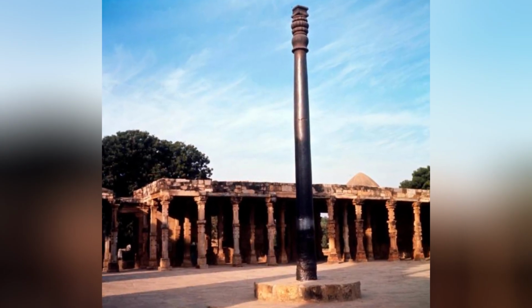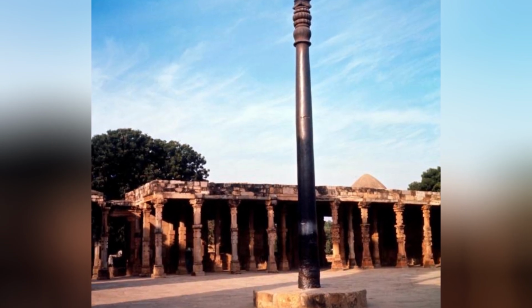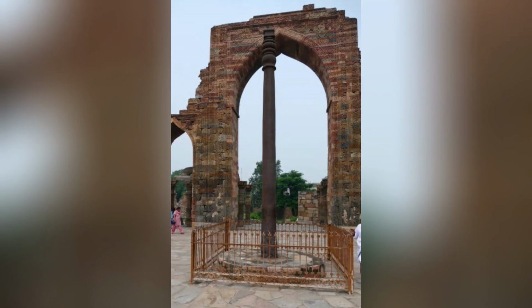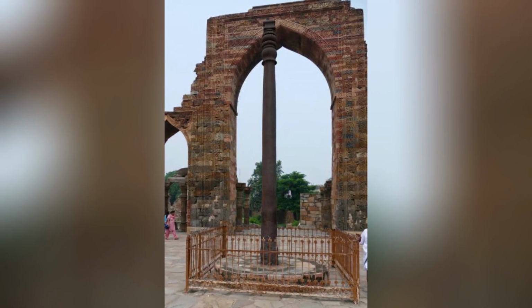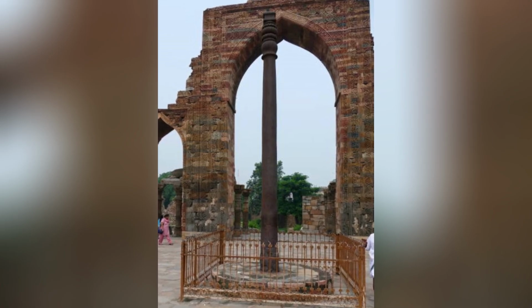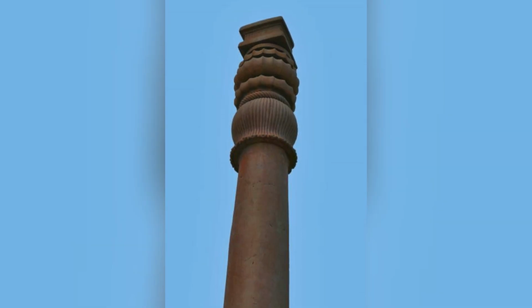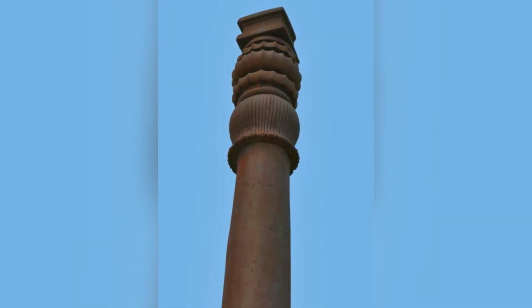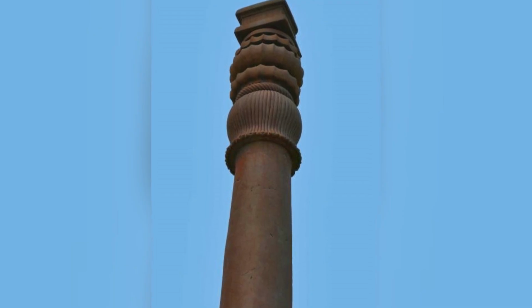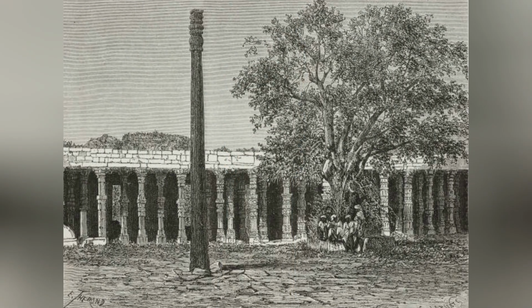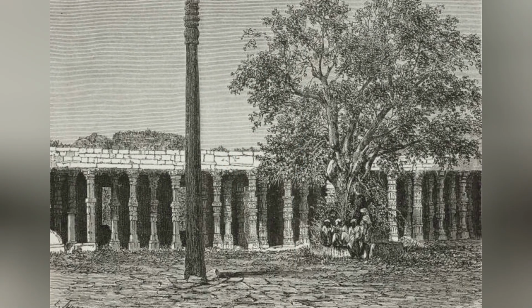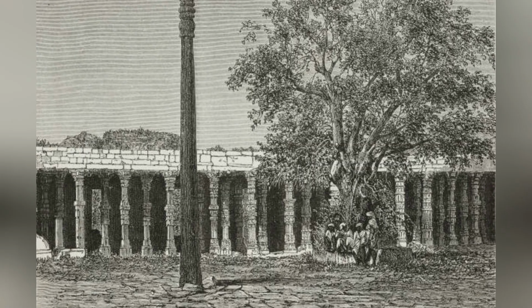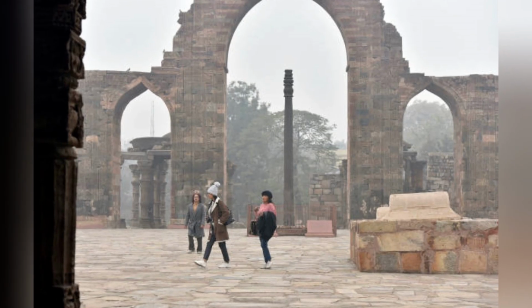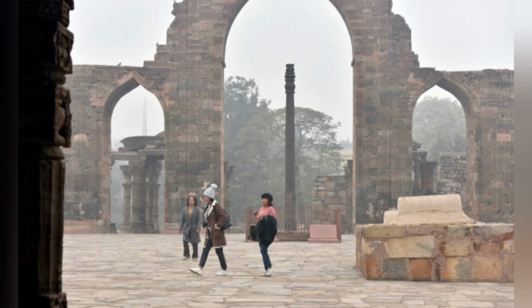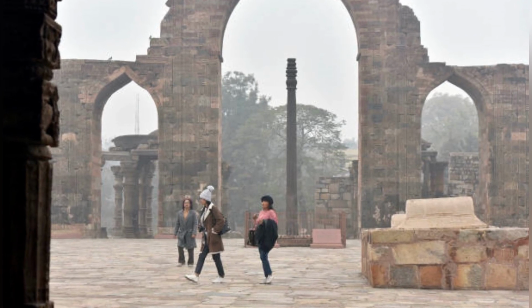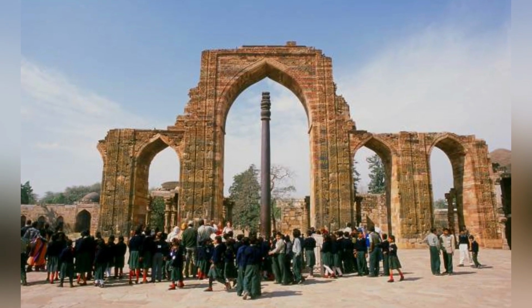The slag inclusions in the pillar's iron, which are a normal feature of bloomery iron, create local variations in the chemistry and the microstructure of the iron's surface that influence the formation and the structure of the protective film. The analysis of the film in the vicinity of the slag inclusions has revealed that the film is thicker and more complex in these areas, reflecting the local chemical differences between the slag and the iron. The influence of the slag inclusions on the film formation is an important consideration for the development of modern phosphorus-containing steels, because the slag inclusions, which are not present in modern steels, may play a role in the formation of the protective film that is not replicated in the cleaner, more homogeneous modern materials.